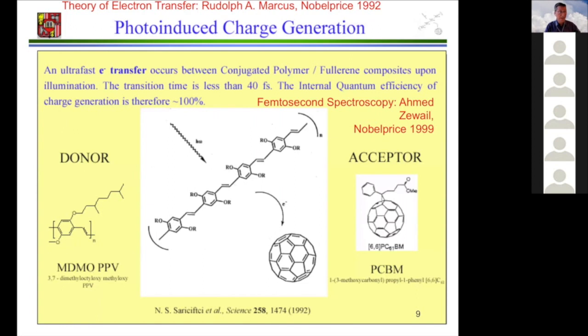In 1992, Sariciftci and Wudl used femtosecond transient absorption spectroscopy to show an electron transfer between such a polymer, polyphenylene vinylene, we call it PPV, and C60, and it happened on a 40 femtosecond time scale. So they used very fast laser spectroscopy, and in 40 femtoseconds, an electron came from the photoexcited donor to the buckyball acceptor. And this was basically the first polymer fullerene solar cell.